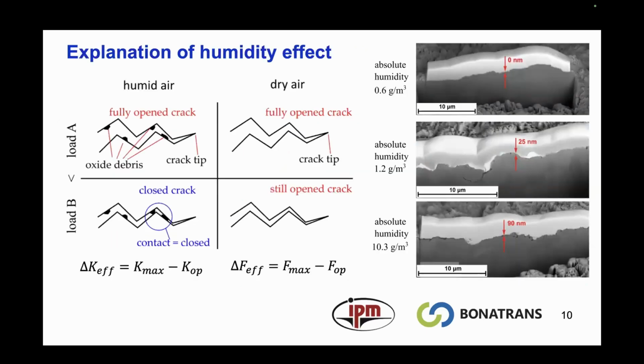What is the explanation of this effect? It is caused by oxide debris developing on the crack faces during crack growth.